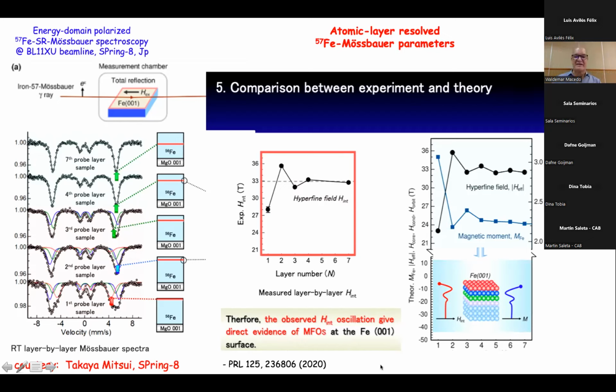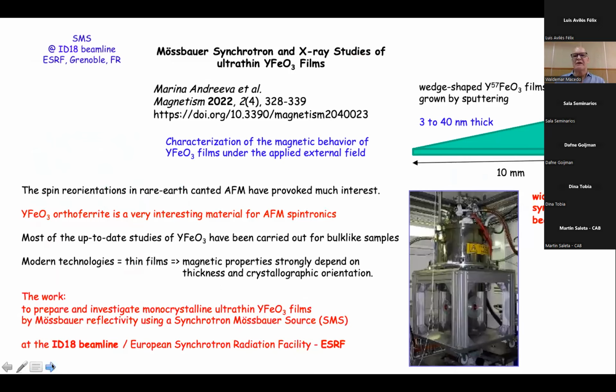This means the first evidence that you have by doing iron-57 atomic layer resolved Mössbauer spectroscopy with the synchrotron, in grazing incidence geometry at SPring-8, they are able to finally show that there really are Friedel oscillations at the surface of the iron-57, of the iron 001 surface. That is what you can do nowadays by using this approach. I want to show you one more result for that.